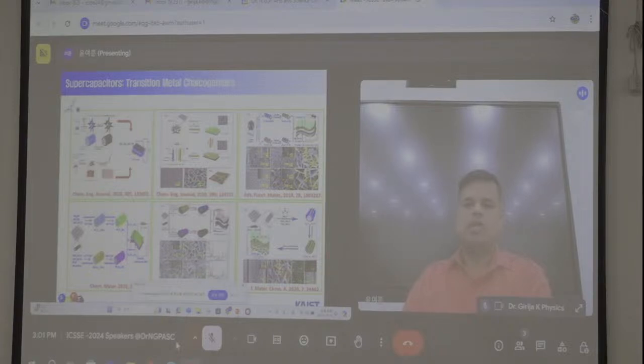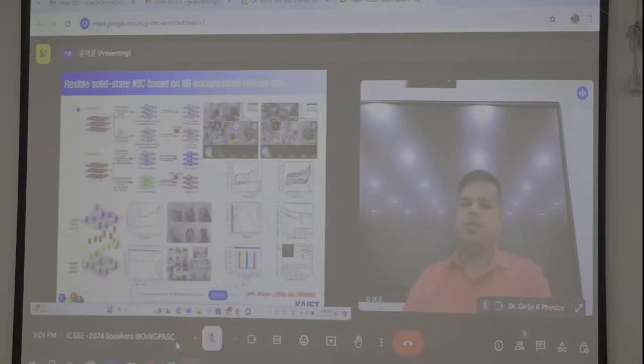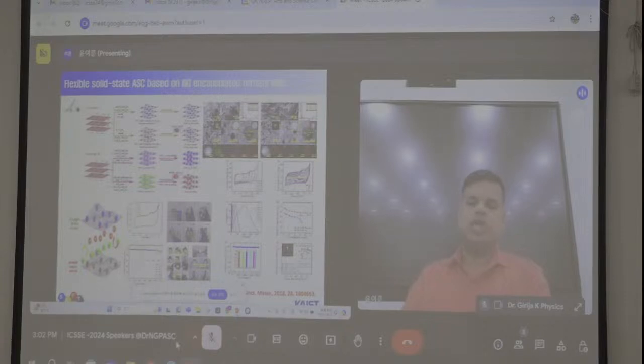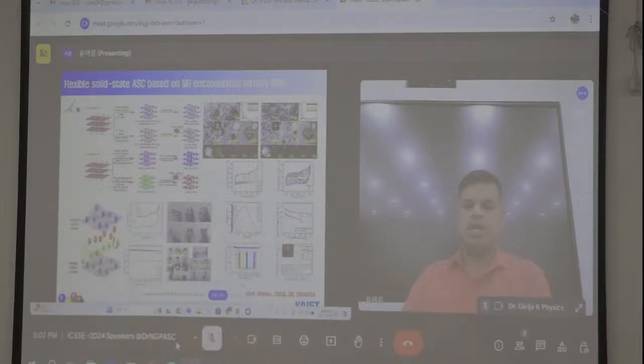We also developed a first sulfide based material for flexible devices, and selenide, phosphide and some telluride based materials. You can see some strategy: usually for making metal nitride they need ammonia gas, but in our case we make it without ammonia gas, because the ammonia annealing process may be hazardous to the environment. Therefore, we do some interesting things for ammonia-free pyrolysis. We make the metal nitride in a core shell, and finally we tested with different bending and flexible devices, and we also achieved high energy density and power density.